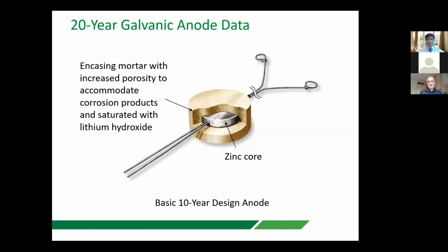But there had to be a bit of development to try and convince the zinc that we were using as the core material. Zinc is obviously more electronegative than steel, and therefore will preferentially corrode if you couple it with steel. But the zinc needs to remain in an active condition. If you put zinc inside concrete at pH 12.5 or roughly that, you would see that it would start to passivate. It would form calcium zincate byproducts. And that would act as sort of a passivation layer on top of the zinc, and soon the corrosion of zinc would stop, and therefore you're not really protecting the steel reinforcement.